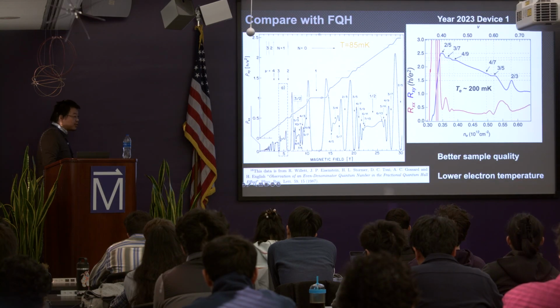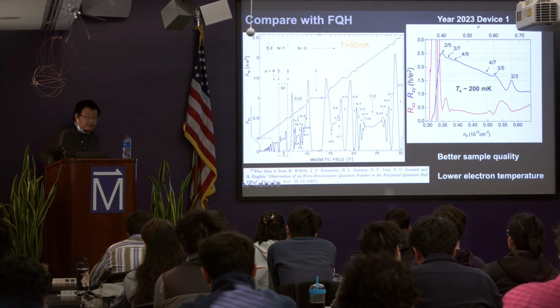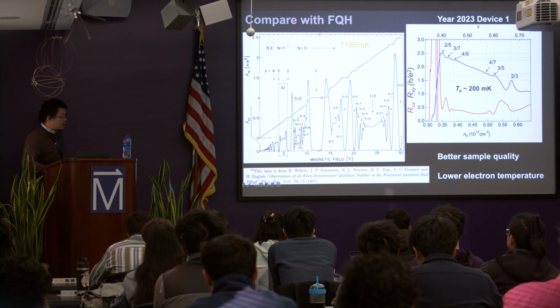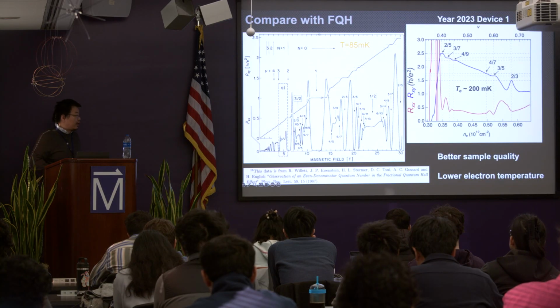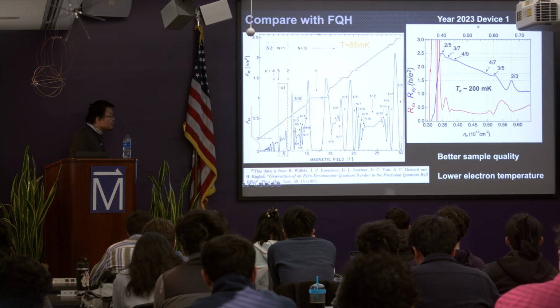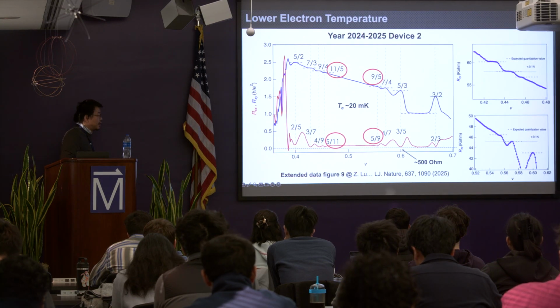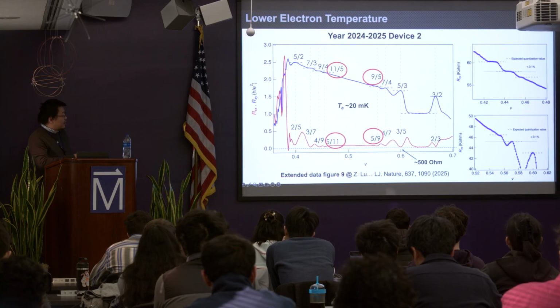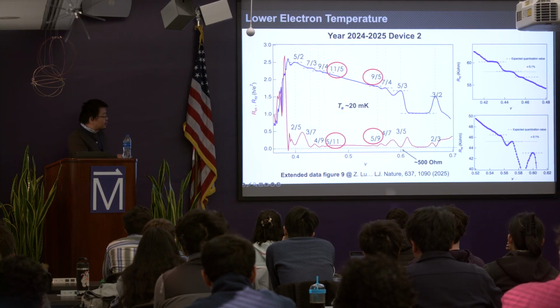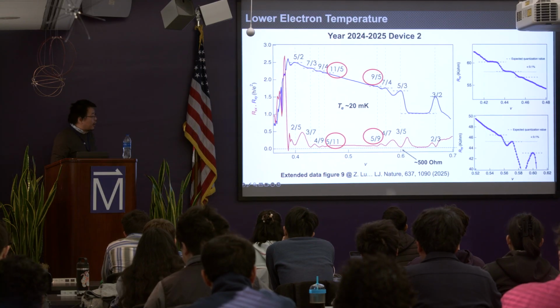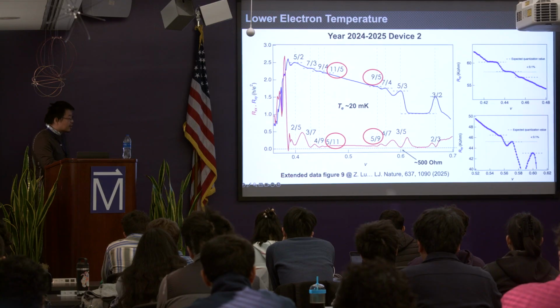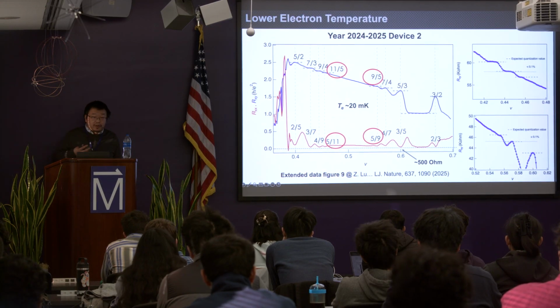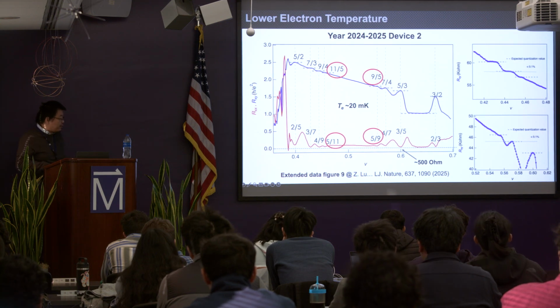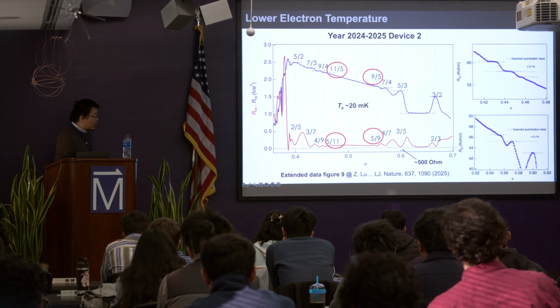This is the fractional quantum Hall data in high field, and you see a forest of fractional states with the improvement of the sample quality and also lower electron temperature. This is done at 85 millikelvin. So we just follow the same route, making better devices and working on the fridge to improve the electron temperature, and this is what we got. You can see there are a lot more fractions, with very good quantization within about 0.1%. You see all these pretty well-defined dips, and before the residue was a few kilo ohms. Now you have a few hundreds of ohms, and if you cool it down even more, it will go lower and lower.